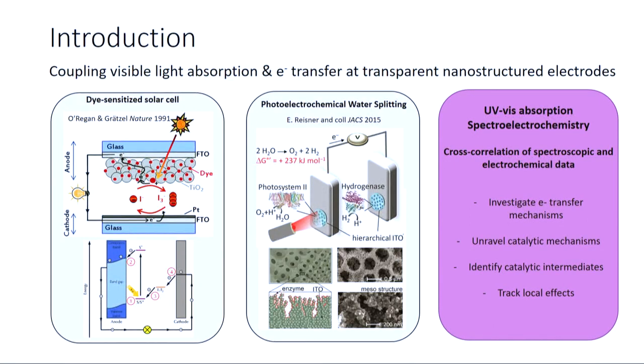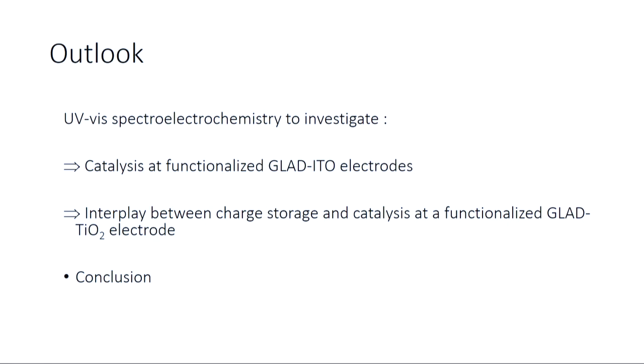And this allows, because of photosystem 2, you can drive photooxidation of water to dioxygen upon light absorption, and this allows water splitting at a bias that is far below the thermodynamic potential that is usually required for water splitting. So for this kind of functionalized nanostructured transparent electrodes, what I would like to show you today is that UV-visible absorption spectroelectrochemistry is an interesting tool to investigate the electrochemical reactivity, and this thanks to the cross-correlation of spectroscopic and electrochemical data. So my presentation will be divided in two parts.